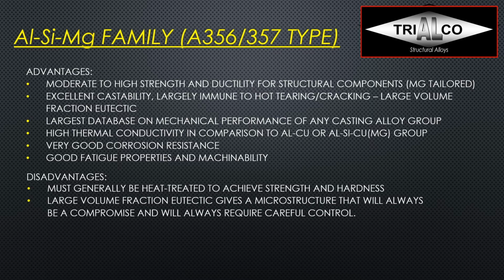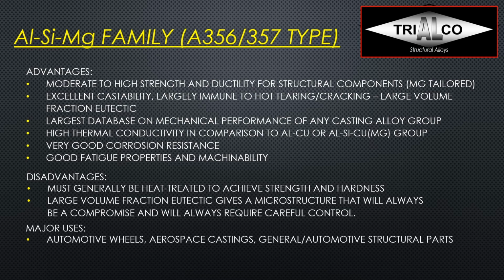The large volume fraction of eutectic gives a microstructure that will always be a compromise and will always require careful control. So we have to add either strontium or sodium to modify it, or we need extensive thermal modification through heat treatment. The major uses here are really for A356, it's automotive wheels and suspension parts. The 357 types are usually aerospace castings that require higher strength. And we see all sorts of general and automotive structural parts. We can also see a lot of general purpose applications, for example, for street lamps, for all kinds of castings that have no other special requirements, like they have to be anodized or so.